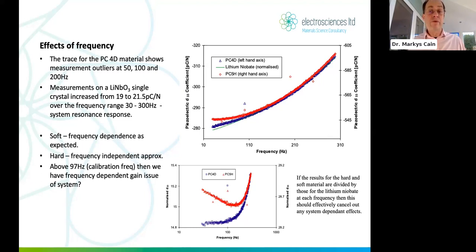and superimpose your data for your device under test. It might be a PC4D, it might be a hard or a soft piezo material. And you can then normalize and subtract this trend in the top graph, which is increasing piezo coefficient with frequency, subtract the lithium niobate, and you get the data in the bottom graph. And that shows you real material property response, because you've now removed instrumentation issues.